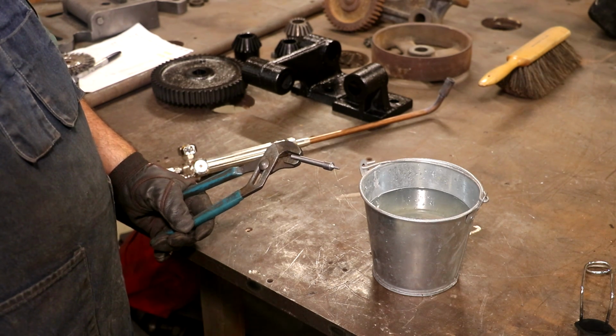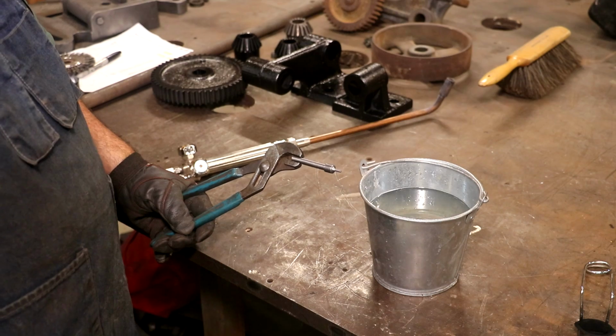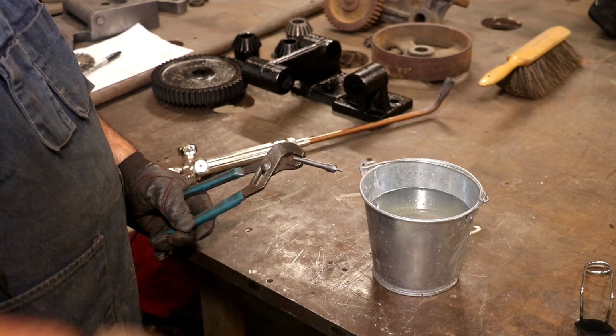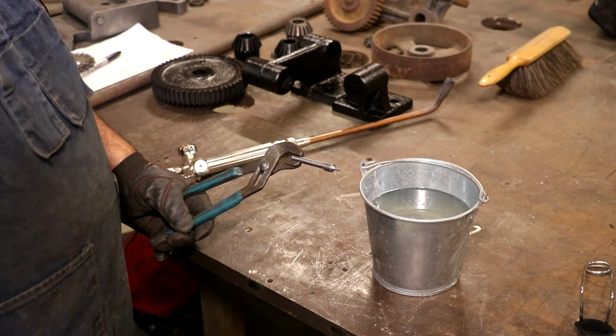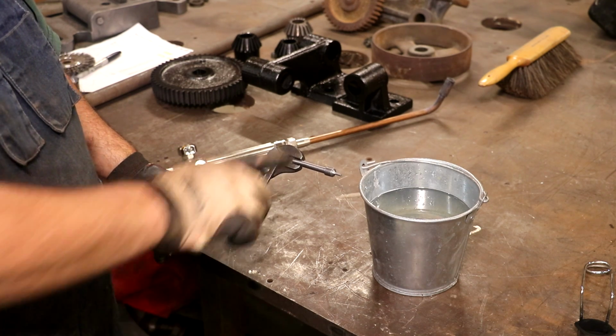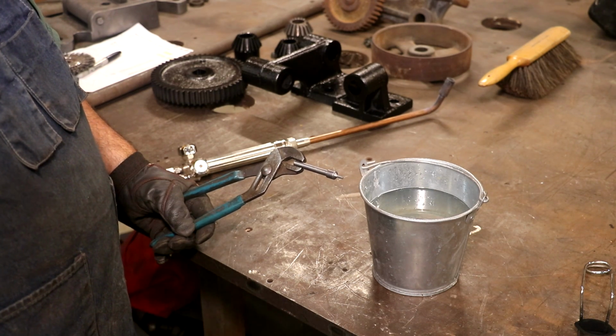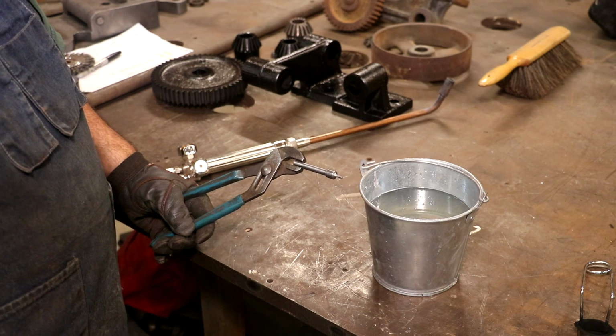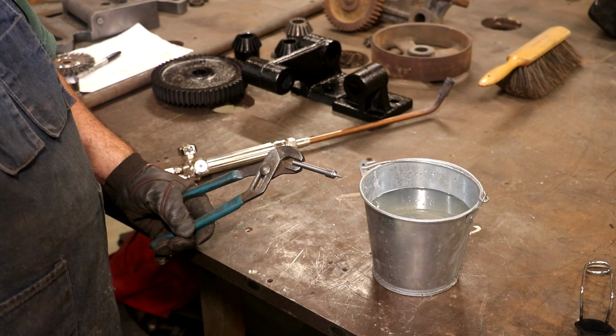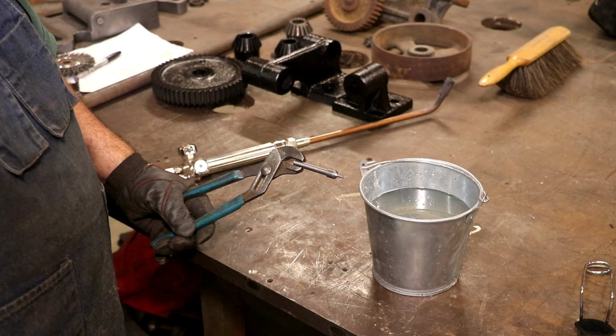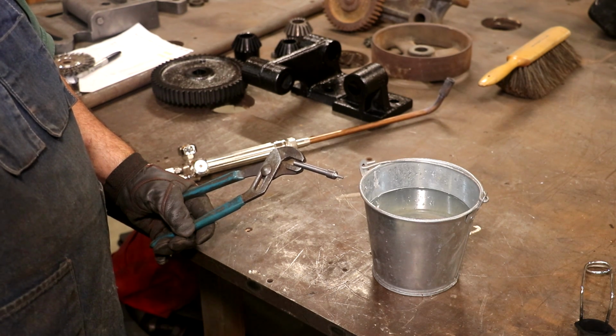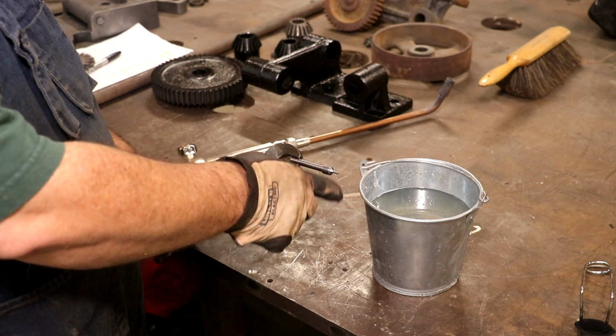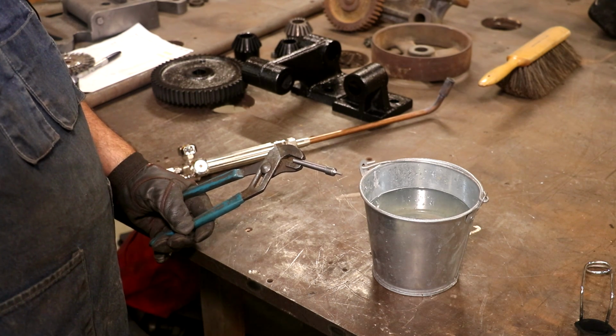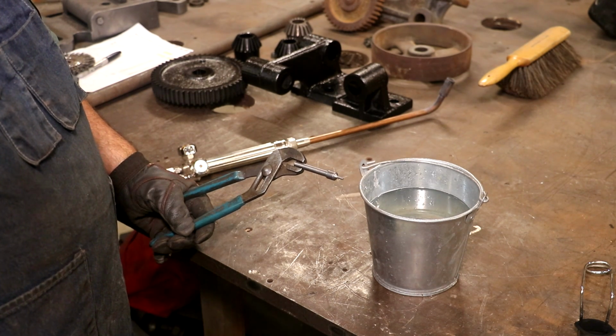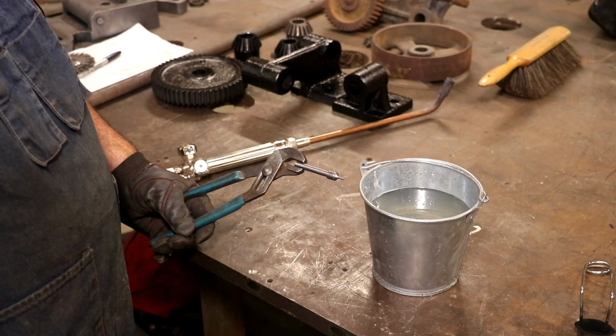And the reason I'm doing it this way rather than using my heat treat oven is, in this case, I really don't want to harden the whole pin. I just want to harden the tip down here, and that's it. So I'm only going to heat the tip up, and we will harden it. Once it's hardened, it's going to be too hard, and we need to back it off a little bit. We'll temper it using the heat treat oven, and I'll go over that in a minute, but that will get it down where it will hopefully be hard and tough, but not really hard and brittle, which is what we want to avoid. So let me get my torch fired up, and we'll get this thing heated up and hardened.